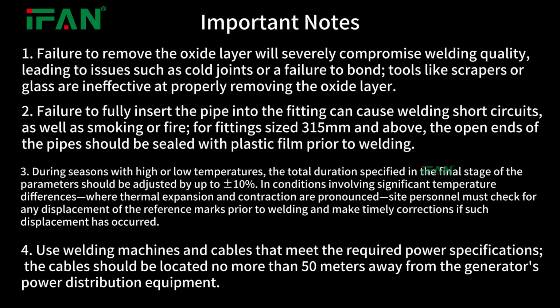1. Failure to remove the oxide layer will severely compromise welding quality, leading to issues such as cold joints or a failure to bond. Tools like scrapers or glass are ineffective at properly removing the oxide layer. 2. Failure to fully insert the pipe into the fitting can cause welding short circuits, as well as smoking or fire. For fitting size 315 mm and above, the open ends of the pipes should be sealed with plastic film prior to welding.